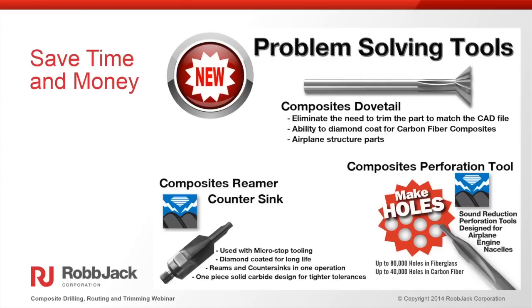By making it out of a solid carbide blank and making the threads out of carbide, we're able to diamond coat it. So it reams and countersinks in one operation, and then you're able to have much tighter tolerances, because whenever you have a brazed tool or you don't have the ability to diamond coat it, you're really trying to chase those tolerances when you're trying to make really tight holes for countersink operations.